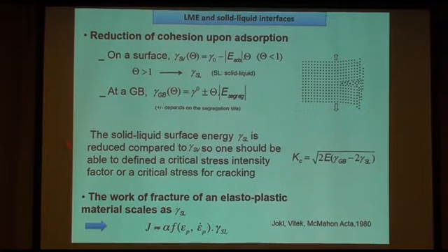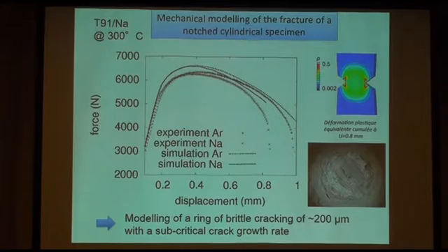But if you look at the case where you have an energy barrier to crack, you should have a dependence on the solid-liquid surface energy, and you should expect something close to scaling of your J integral with the solid-liquid surface energy. So there is a clear link between cracking and the surface energy, and you should expect to be able to describe this with fracture criteria in a conventional way. So we tried to do this with